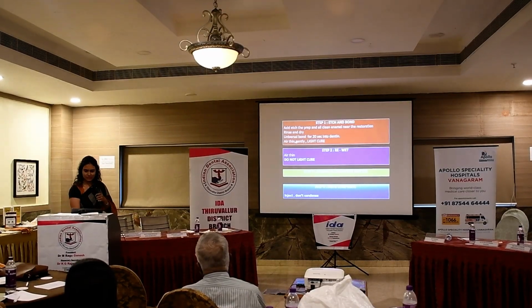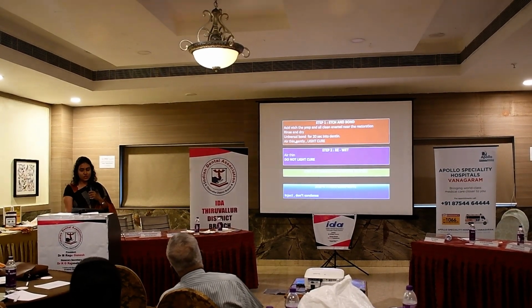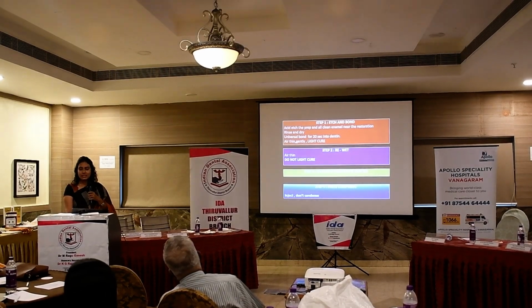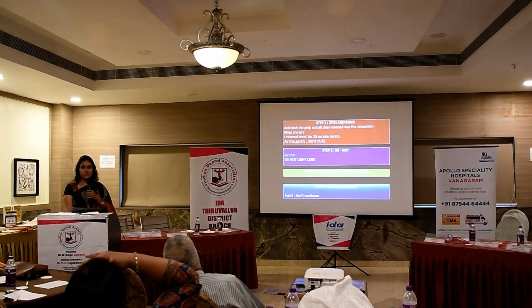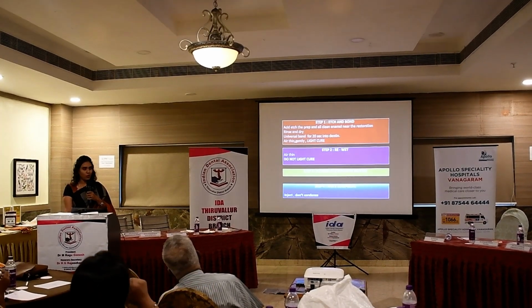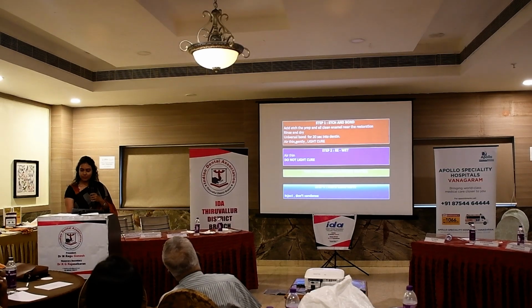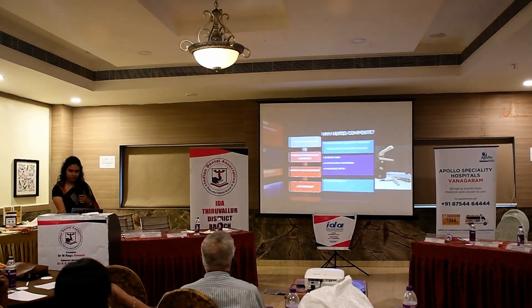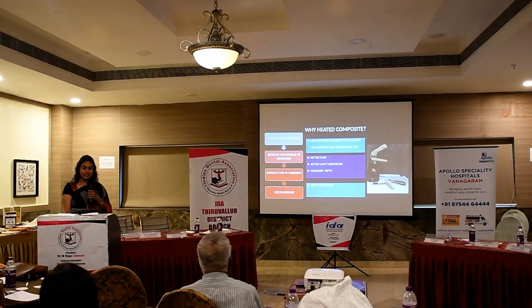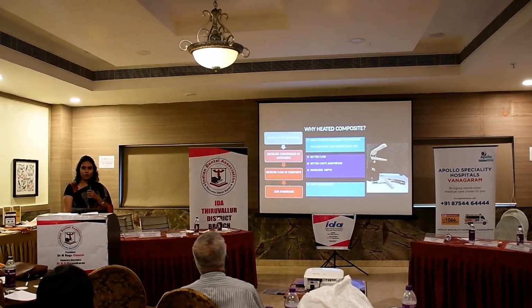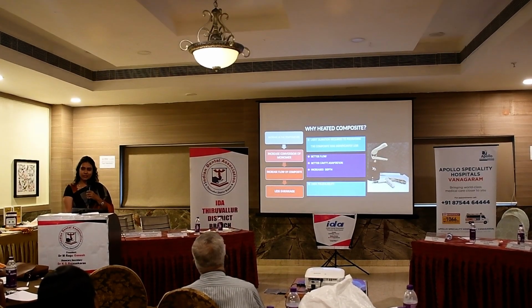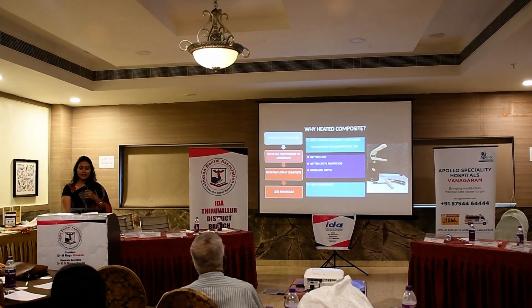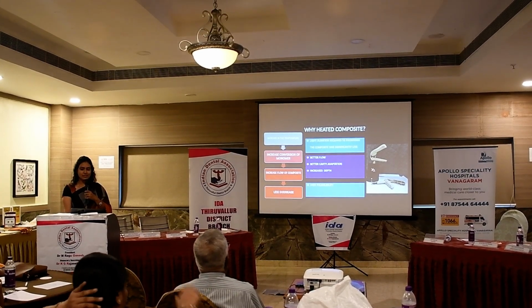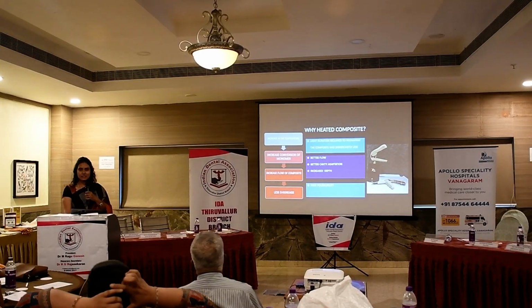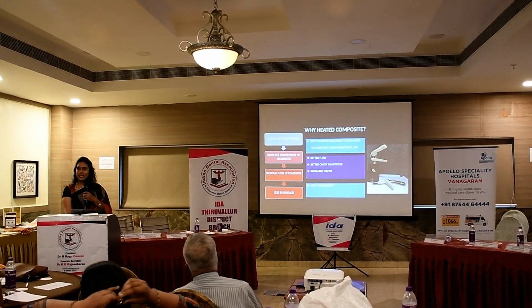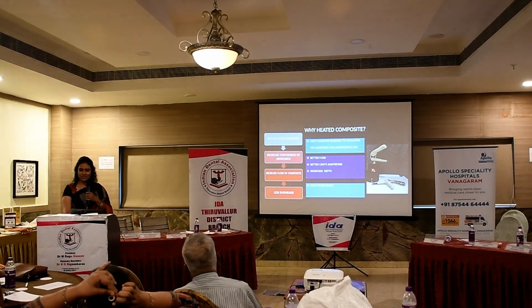Why this injection molding technique? The simultaneous injection of the heated flowable and paste composite results in predictable filling of the cavity. So this overcomes the deficiencies of the layering technique and also gives an excellent finish. Why heated composites? Increase in temperature leads to an increase in the conversion rate of monomer to oligomer to polymer, with increased flow of composite and less shrinkage. The second thing is the curing time required to polymerize the composite is significantly less. Third is better flow, so better cavity adaptation and also increased depth of cure. The fourth thing is high polishability.